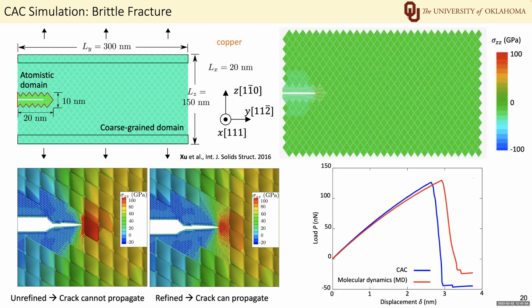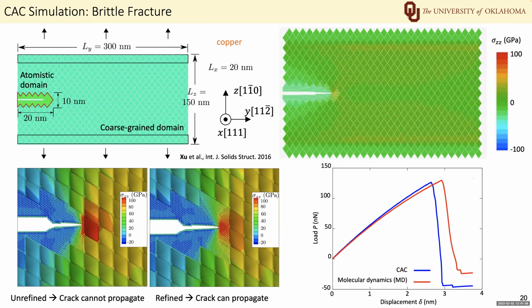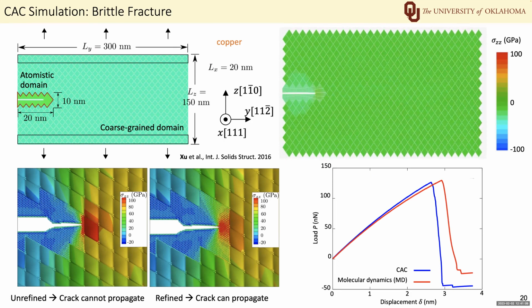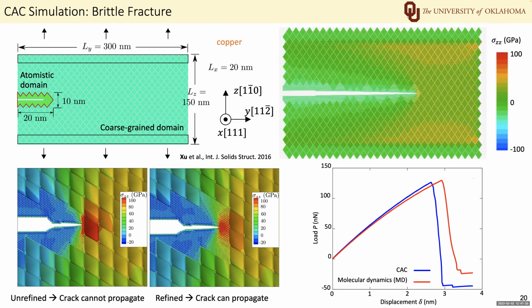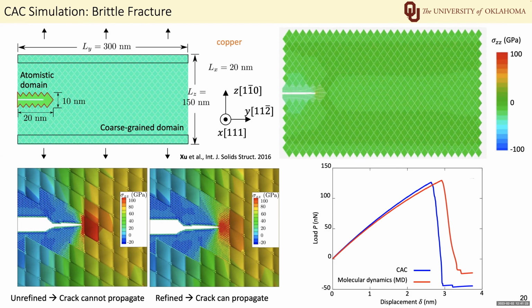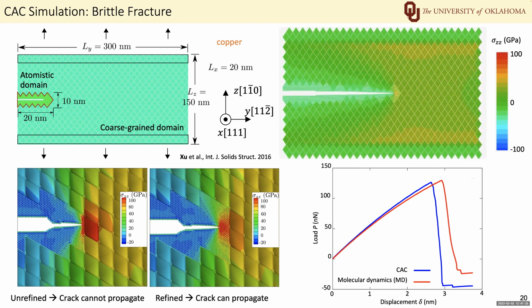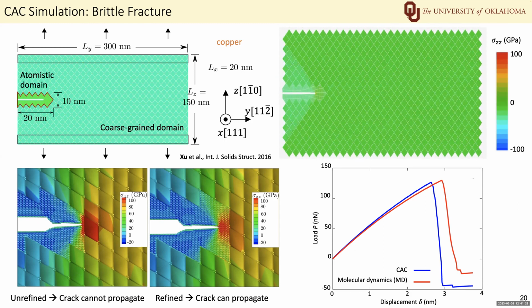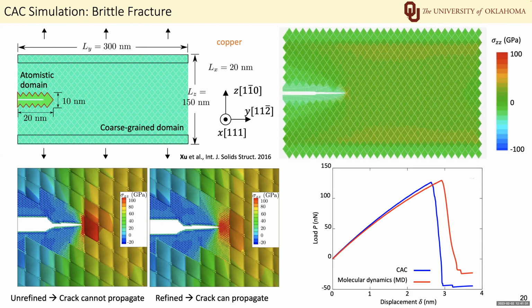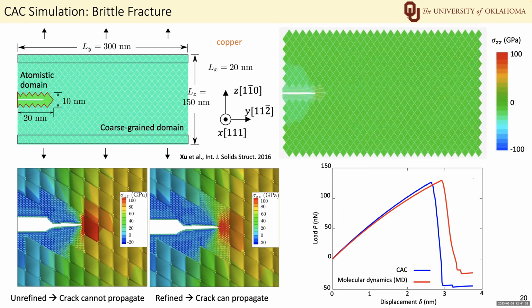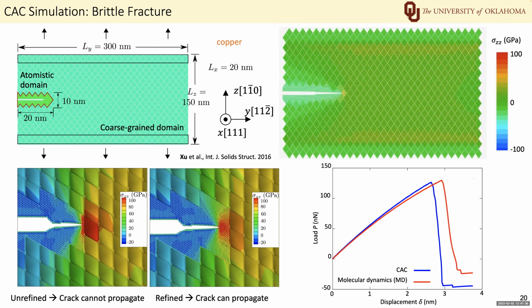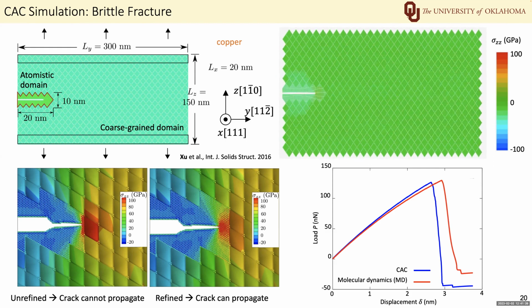So with that in mind, I track the position of the crack tip and adaptively define some finite elements to atoms. So we found that the crack could propagate without the dislocation nucleation, suggesting that this is the brittle fracture. The displacement curve predicted by CAC is similar to that by equivalent molecular dynamics simulation.